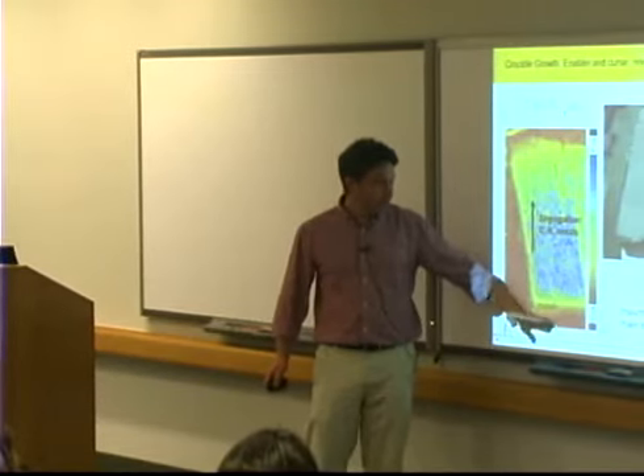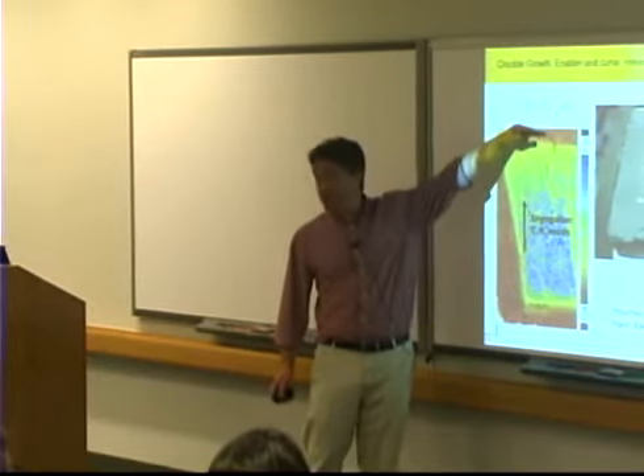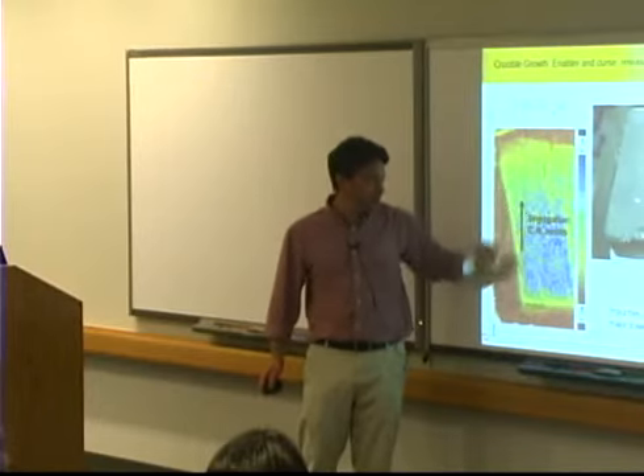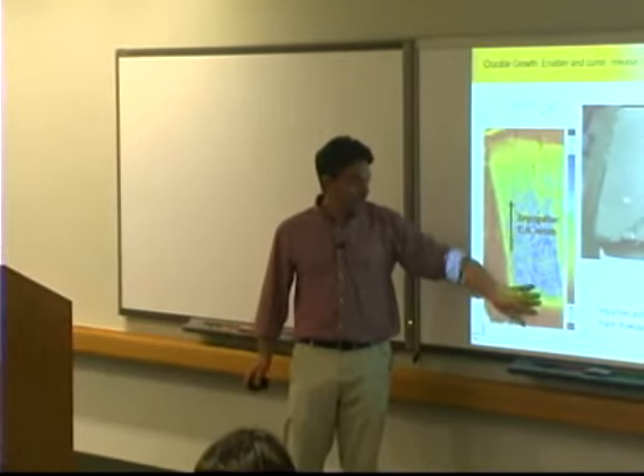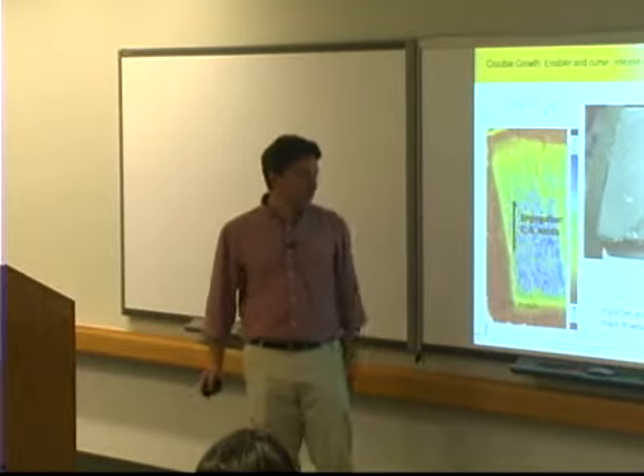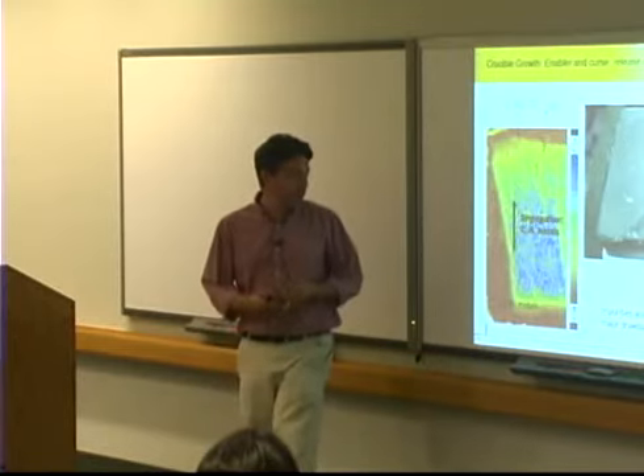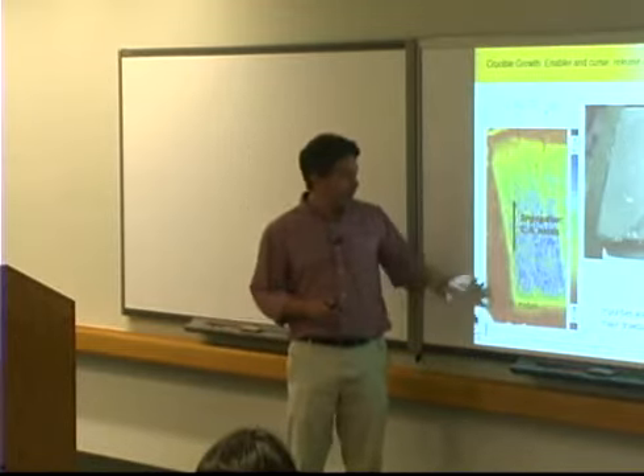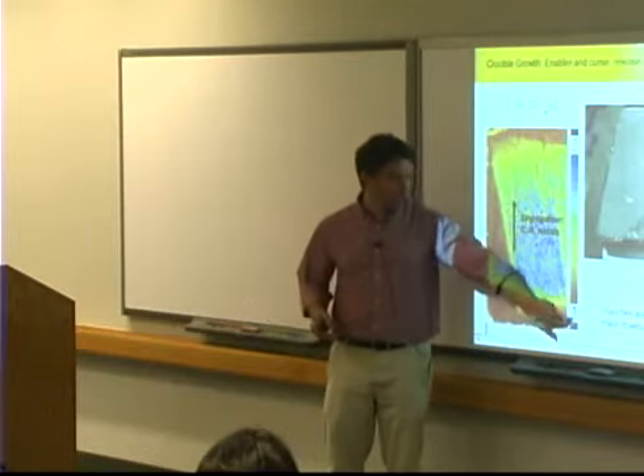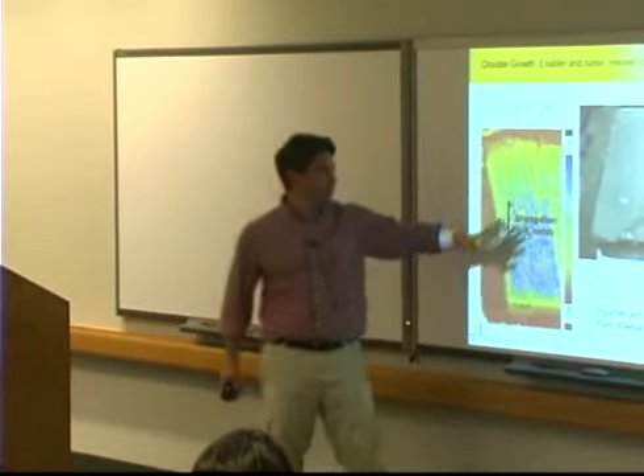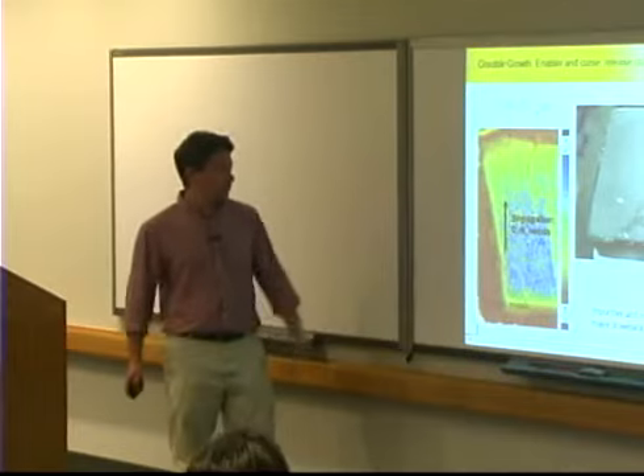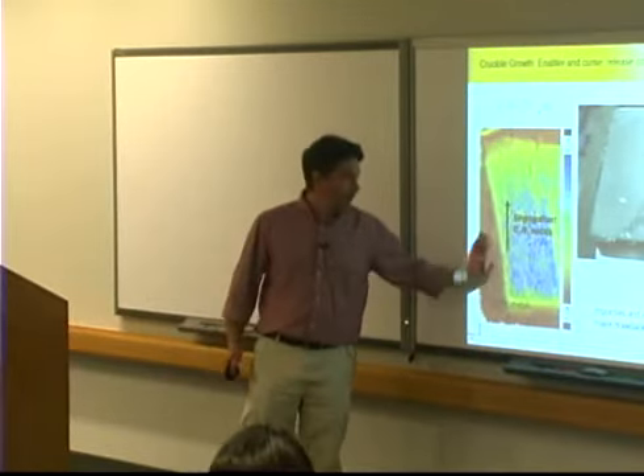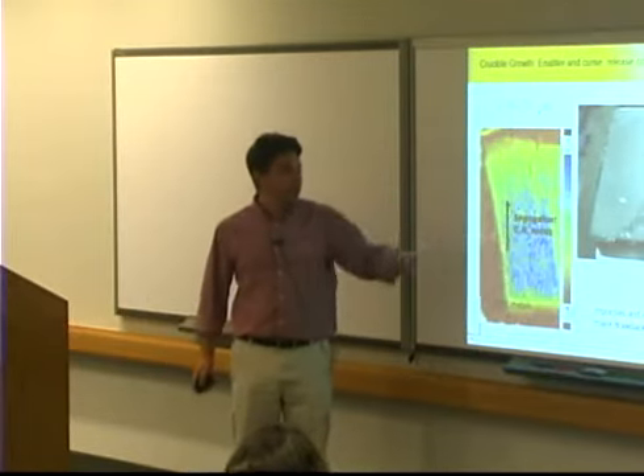And so you have basically the entire process time while you're solidifying this that impurities diffuse in. And these impurities end up cutting down on the lifetime of the material. So this is a minority carrier lifetime. And in this case here, you can see red is bad and blue is good. And so you get stuff coming from the bottom and in from the sides, and it ends up being a bad thing.